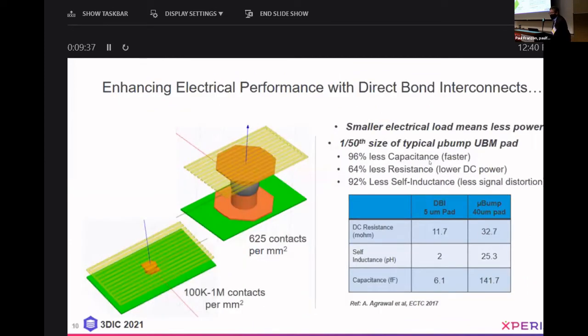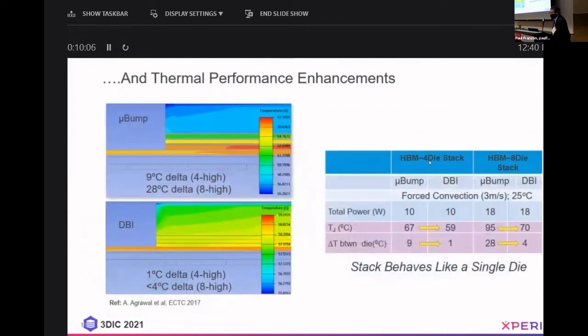This was some modeling that was done to show the enhanced electrical performance. And as we saw from the last talk, there's basically reduction of capacitance for faster performance, less resistance for lower DC power drop and less heating. And there's less self-inductance as well for less signal distortion. And again, with the thermal performance, we found that the stack with the DBI hybrid bonding acts more like a single die than the microbump stack.